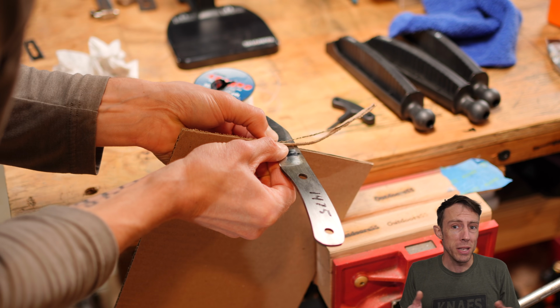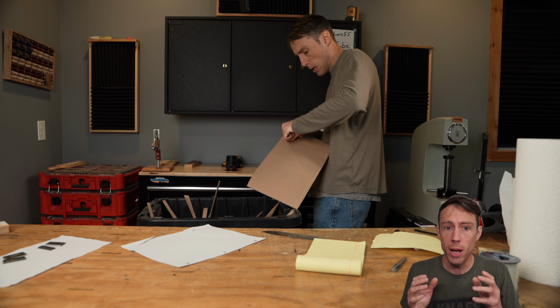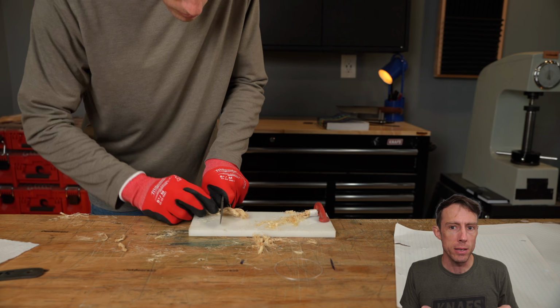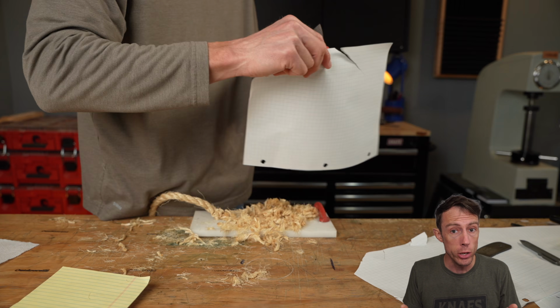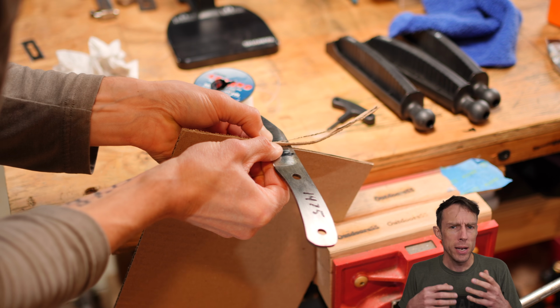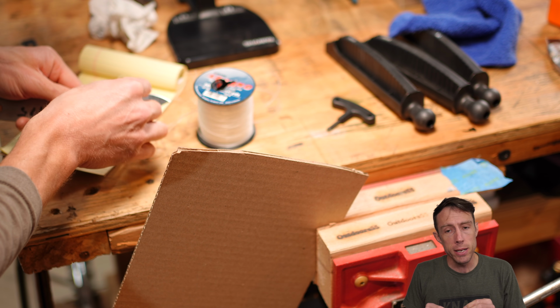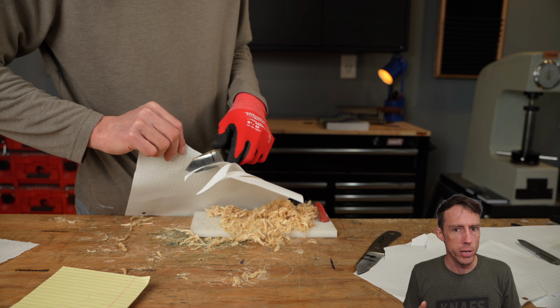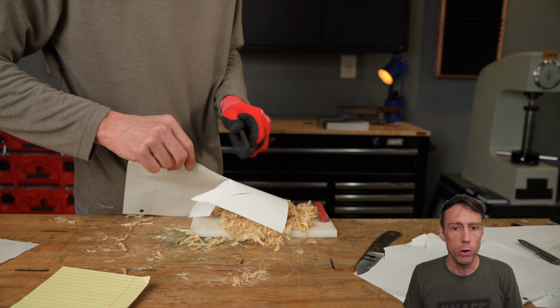So with both of our test blades, I did some edge retention testing. I did cardboard testing and rope testing to see if there was any difference between the good heat treated blade and the bad. I did some fine edge retention tests and I did some working edge retention tests with both cardboard and rope. And guess what?